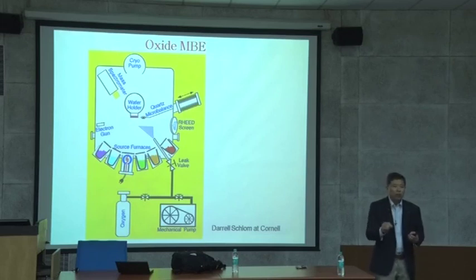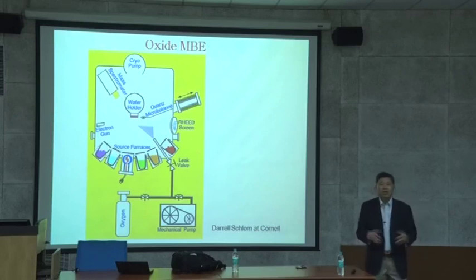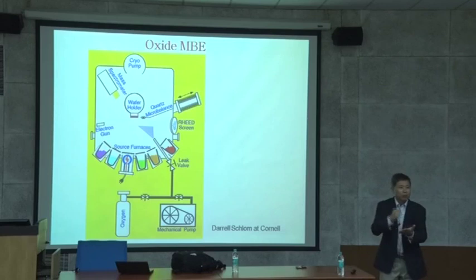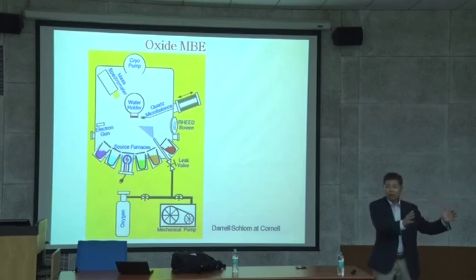It's an yttrium barium copper oxide, exactly 1:2:3 compound, actual phase, exactly the same structure. And then you make this bulk material, and this bulk material synthesis is something any lab can do. You only need a mortar for grinding, a weighing machine, a ball mill, a furnace, and a press, that's it. And we have our lab, even though we have a thin film lab, and we have a dedicated powder lab for making all the targets.